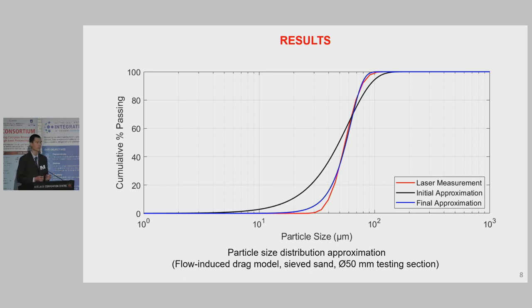With a flow-induced drag model dynamically tuned online, it agrees well with the actual size distribution on convergence. But we still see some error for particles below 30 microns. This is because the approximation function we used was derived from statistics. So when the actual size distribution of the sample deviates from statistics, then we will have some error in approximation. But in terms of P80, 70 microns, this approximation still gives us very good results.